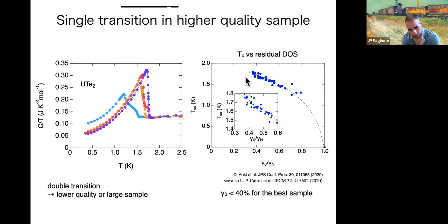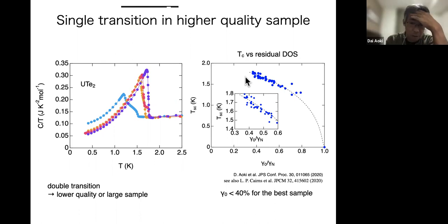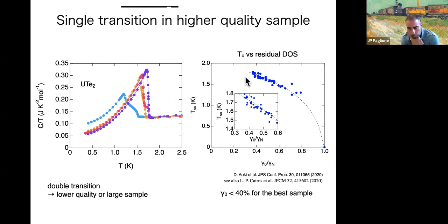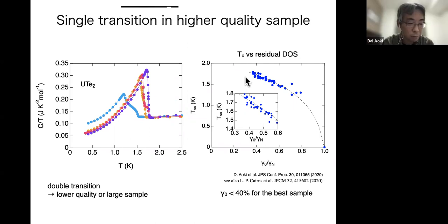Okay, I was just curious because I wonder if you have any other data like X-ray or anything else that indicates quality. X-ray is always good, but by NMR experiment we measured the NMR spectra of the superconducting sample and the non-superconducting sample. In the non-superconducting sample, the NMR spectrum is quite broad compared to the superconducting sample. So the superconducting sample is a very good crystal. This is for sure. This is interesting. Okay, thank you.